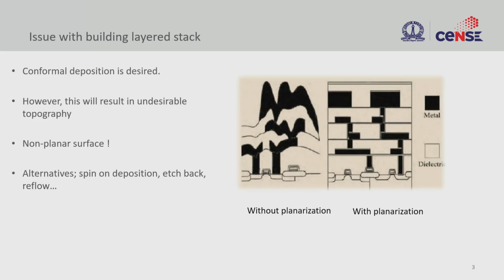Let's look at some general expectations from the wafer fabrication process. What are the issues that we face when we build a multi-layer stack? We tend to use conformal deposition, which gives very good fill, but this normally results in a topography. That means it's not going to be flat anymore. That's what we call a non-planar surface. This is the result of such a conformal deposition. You always have this sort of neck that is formed, and the subsequent layers are going to follow the same topography.